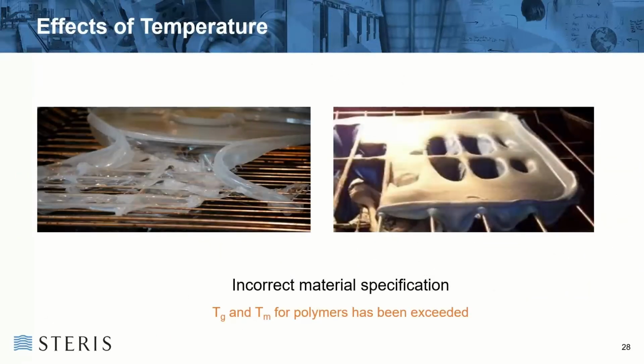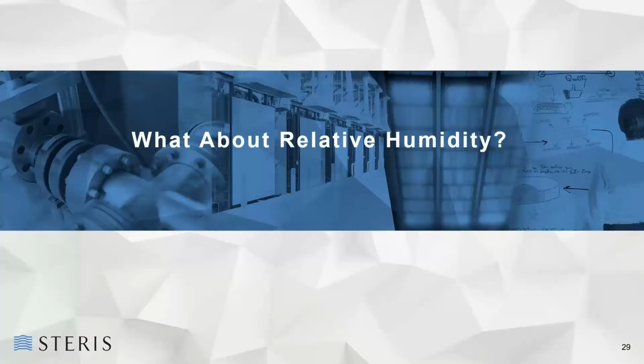If you look at the materials here in the pictures, as you can see, the customer or the designer of this didn't take into account either the glass transitioning point or the melt point of the actual package and or the product. And it took longer to actually clean out the chamber after the test than it did to actually do this damage. And needless to say that the aging failed. Again, because the glass transitioning point of the polymer had been exceeded drastically.